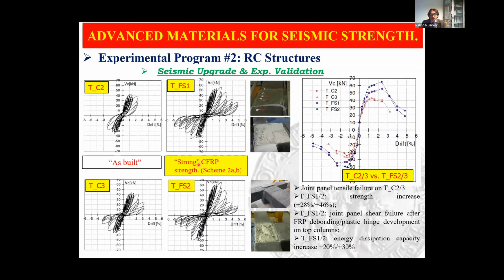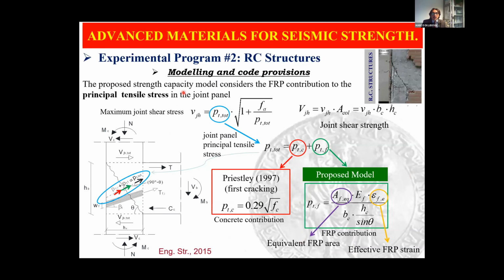In case of strong scheme, so by adopting the more invasive solution, again, the comparison between control specimen and strengthened ones, and here you can see the envelope curves for the control specimen and strengthened ones. In this case, we achieved a more significant strength increase, up to 28 and 46%. And in this case, we obtained the maximum performance because we also avoided the joint shear failure, which was not avoided here because we used just one layer. But by using two layers, we avoided the joint panel shear failure and we attained the plastic hinge. And this was the reason why we attained also the maximum ductility and the maximum energy dissipation capacity, which was about 30%.